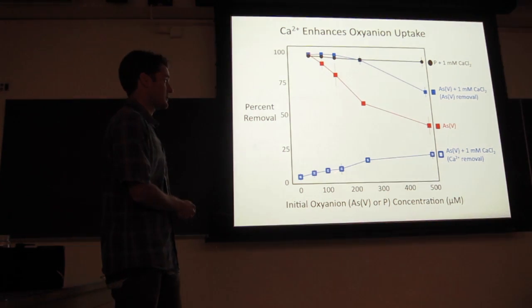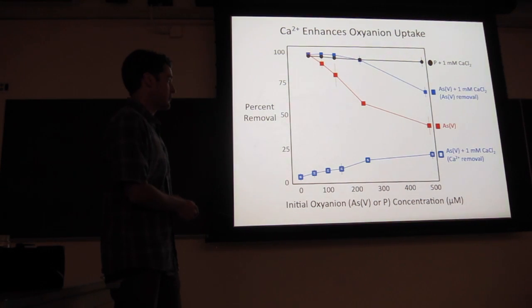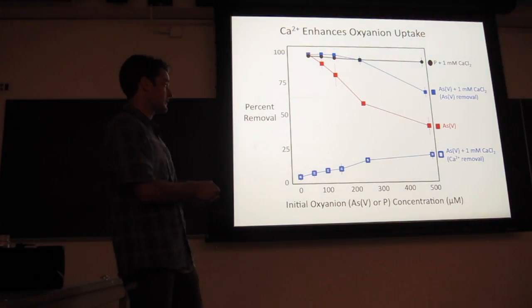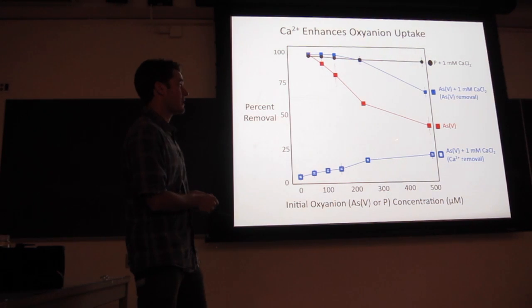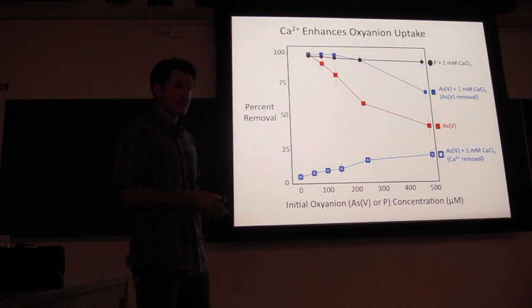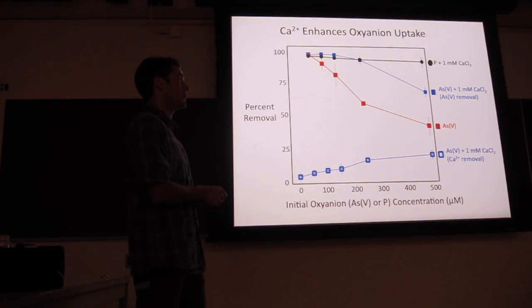So in the open squares, I'm plotting calcium removal. And you can see that calcium removal increases with initial arsenic concentration. And calcium removal, if I were to plot it, in the phosphate system, calcium removal would be even higher.